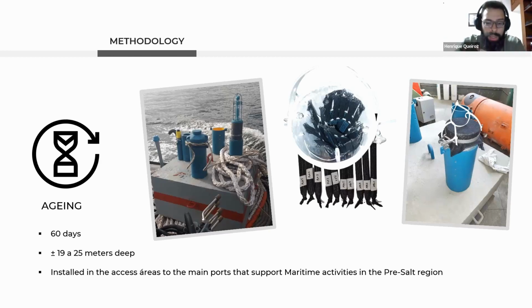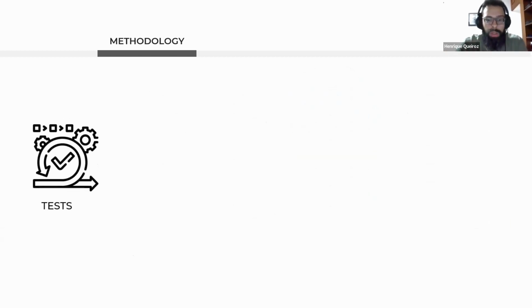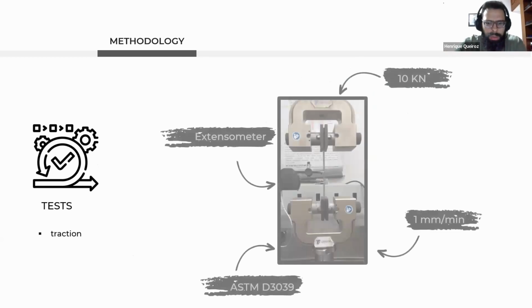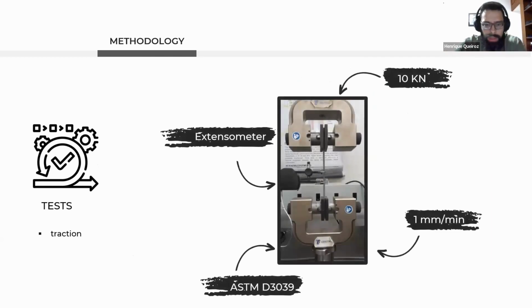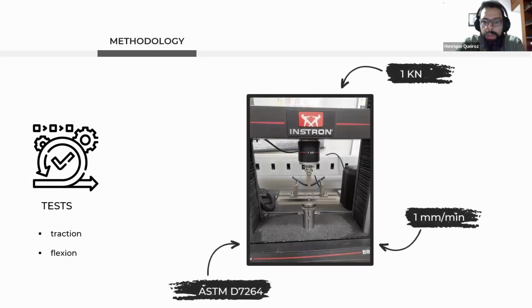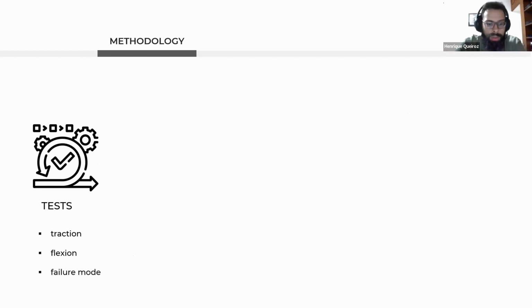And so we use that to do the aging of the specimens. So the testing was pretty simple. We have our classic tensile testing, right? With our 10 kilonewton load cell, 1 millimeter per minute displacement based on ASTM standards, and the same thing for flexural testing with 1 kilonewton load cells, just to have our baseline mechanical properties of the materials. And we also assess the failure modes with simple microscopy using an optical microscope.